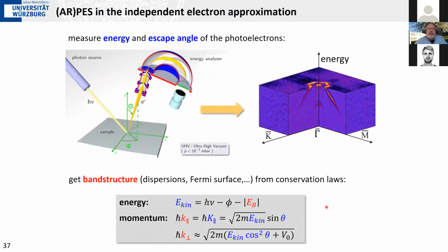Okay, and with this we have all the ingredients that we need to do band structure mapping. We measure all these blue properties here: the kinetic energy of the photoelectrons, the momentum that we have in the vacuum, the escape angle of my photoelectron relative to the surface normal. And from that, I can then calculate the binding energy, if I know the work function, the parallel momentum, which is conserved here, and the perpendicular momentum by the method that I just described. And once you have that, then you can map out a band structure.